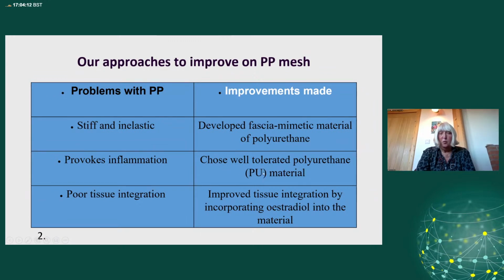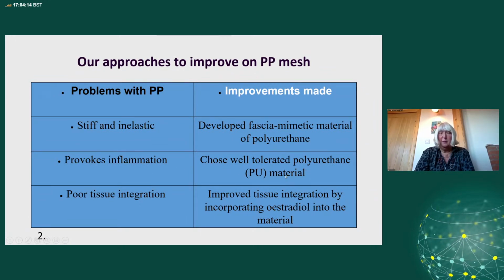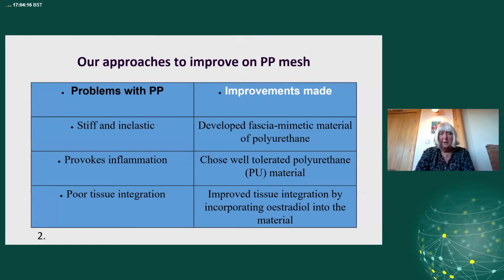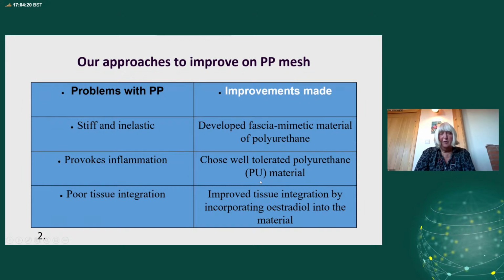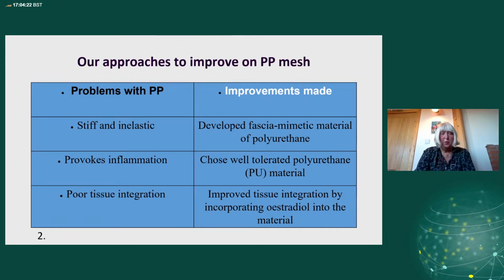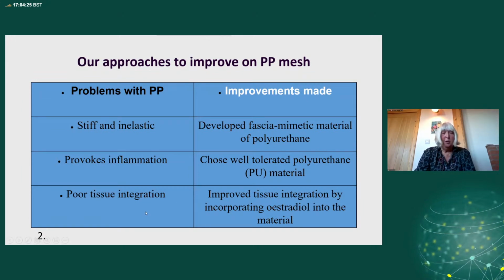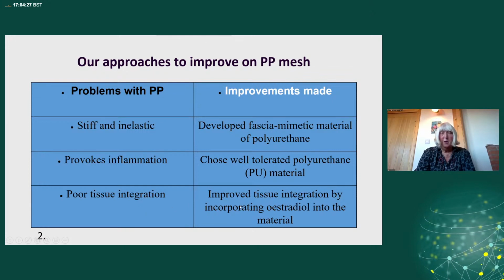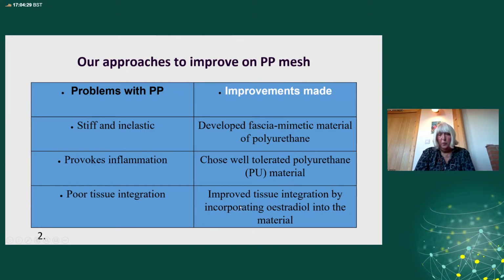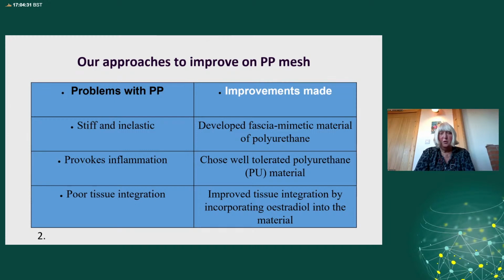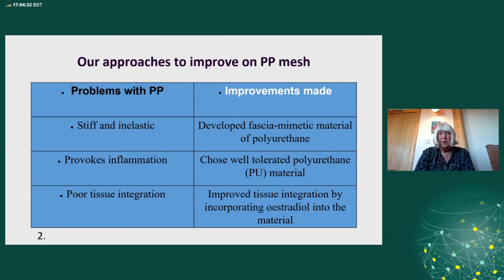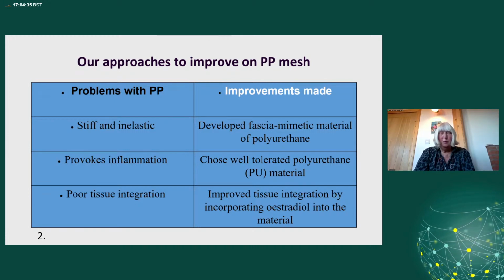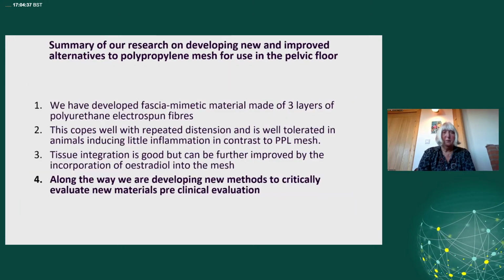We knew there's a lot of information that polypropylene caused persistent inflammation. So we selected a well-tolerated polyurethane that had been used before clinically. And this does cause a certain amount of inflammation, but this is attenuated quite quickly. Polypropylene, poor tissue integration. We found our material did pretty well when implanted in animals, as I will show you. And we've also done some work incorporating estradiol to improve the tissue integration.